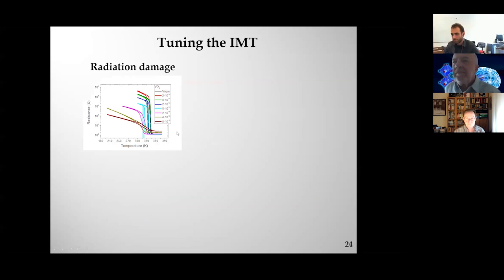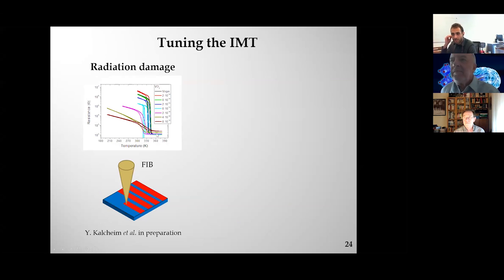Yes. So actually, what I showed you, let me share my screen again. What I'm showing you here was done at high energy. We have done oxygen and helium irradiation. I think it's in Strasbourg, but I'm not sure. And these are 100 kiloelectron volt ions. So this is high energy, in which the ion just pierces through the film without getting implanted, just creating disorder. But whenever we do it with FIB, which is lower energy, and it's gallium ions, we get a lot of implantation. Actually, gallium gets implanted in the film, and the results are very similar. We actually didn't publish this yet, but the results are very similar to what you see with high energy. So in principle, both of them would be an opportunity.